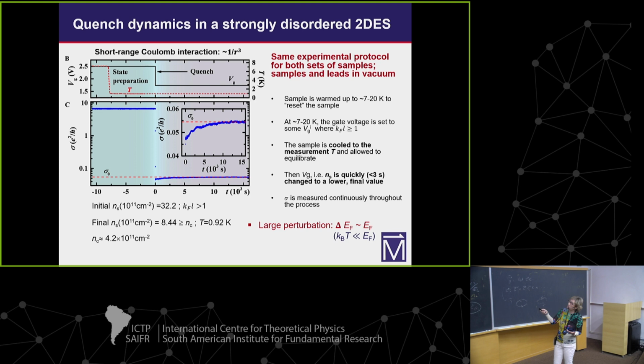You can see that the conductivity drops quickly, and then it increases. The insert is actually a blow-up of this. And you can see again that it takes many hours for the system to reach this, what appears to be equilibrium or some steady value.